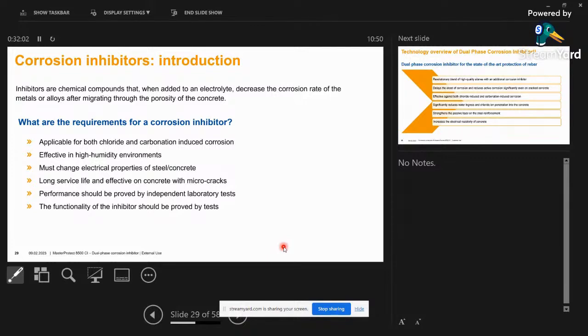It should be effective not only in dry conditions where the activity of corrosion is very less, but it should also be effective in high humidity environments, especially the marine conditions where corrosion activity is much higher, with different cycles of low, medium, and high corrosive activity because of the changes in the humidity and atmospheric conditions. It must change the electrical properties of the steel and the concrete. That means a good corrosion inhibitor has to be reactive, and it should not adversely affect the quality of the concrete. Rather, it should only add to the quality of the concrete. So that should be the role of a corrosion inhibitor.